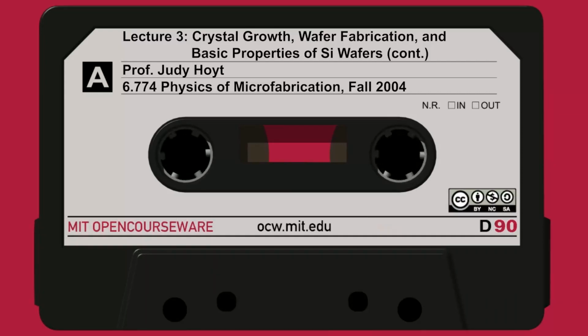Remember, we said the concentration of these charged vacancies is always in the 10 to the 12th, 10 to the 14th range, much smaller than the concentration of electrons due to the dopant atoms. Our doping is usually over 10 to the 14th. We typically dope 10 to the 15th, 10 to the 16th, orders of magnitude above that. So we set the Fermi level just by the dopant concentration, just by the amount of arsenic or boron. That fixes the Fermi level, and then we calculate where the vacancies are based on those equations on the previous page. So there's a lot of simplifying.